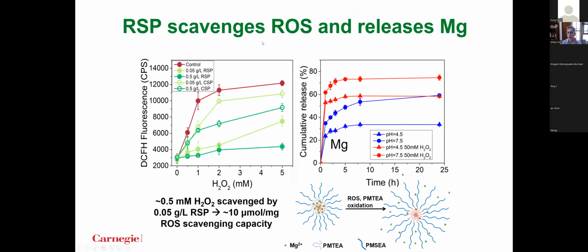All right, so the first question we had is, do they scavenge ROS and do they release magnesium in response to that? So what you see here on the left is this fluorescence signal. And if you're quenching fluorescence, that means you're scavenging reactive oxygen. And we're just putting hydrogen peroxide in as our reactive oxygen species. So if we have a control, we're making a lot of this fluorescence due to the reaction of the dye with the H2O2. And if we put in 0.05 grams per liter of a control polymer, so this is our non-reactive one at a low concentration, there is a little bit of scavenging going on, but not very much.